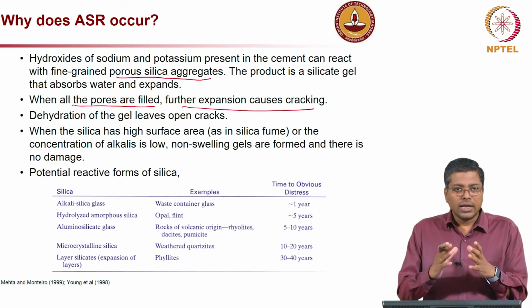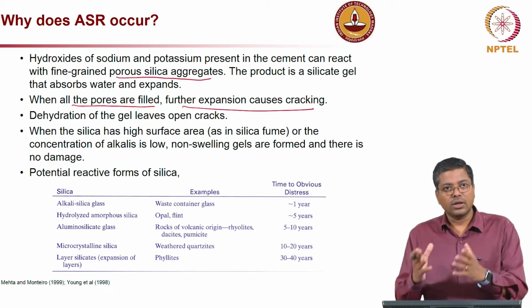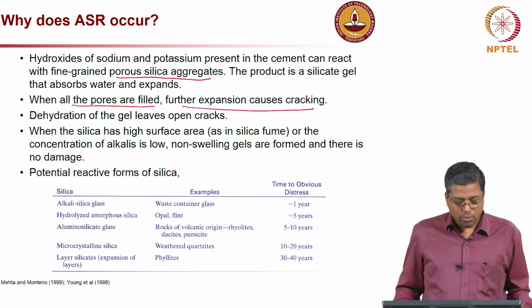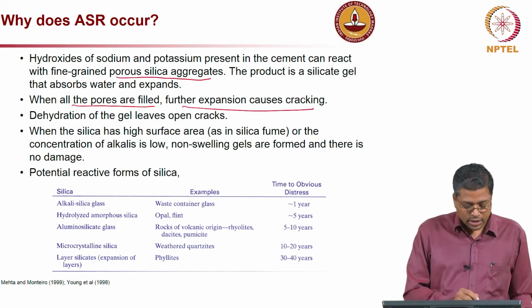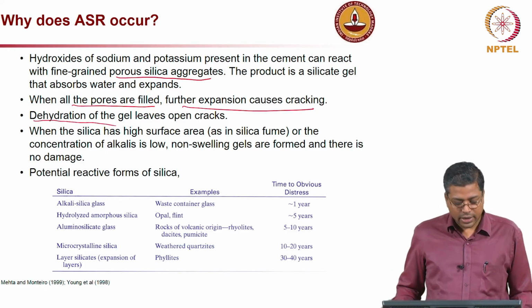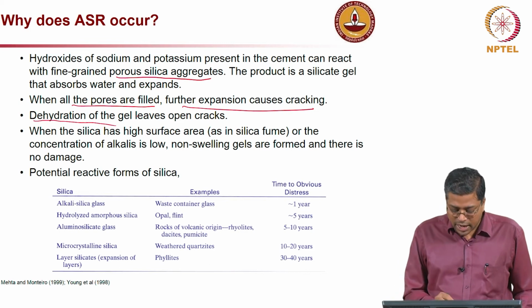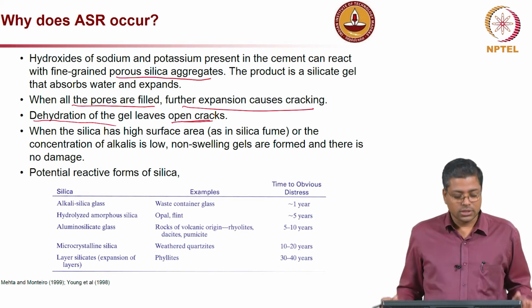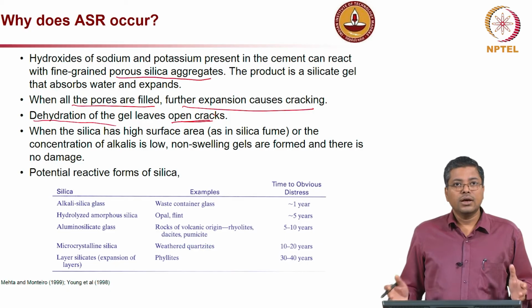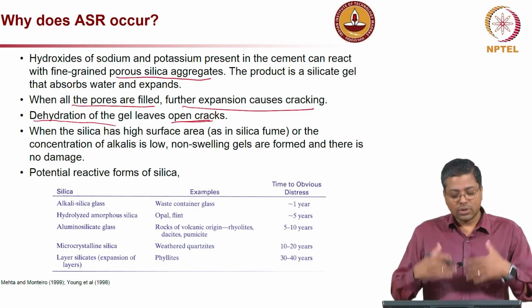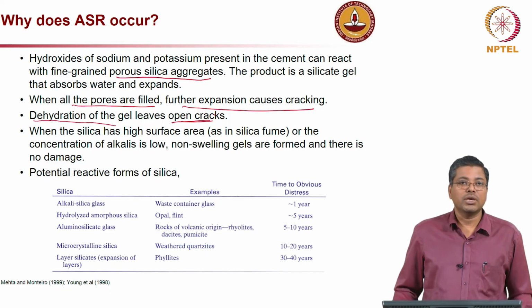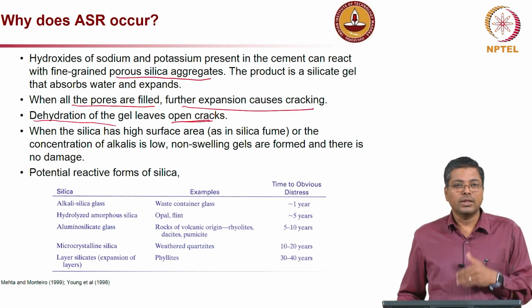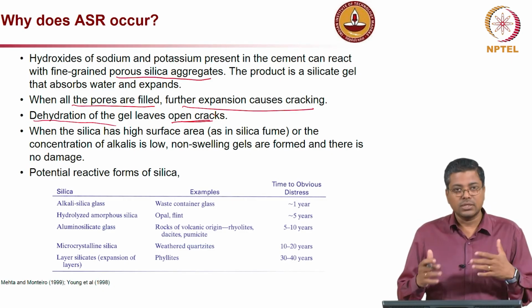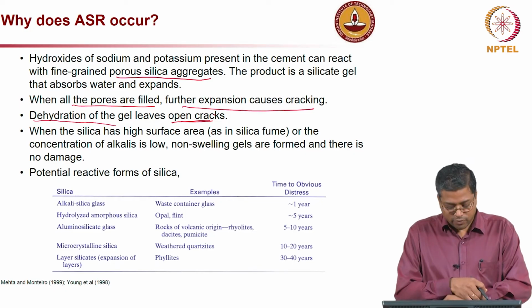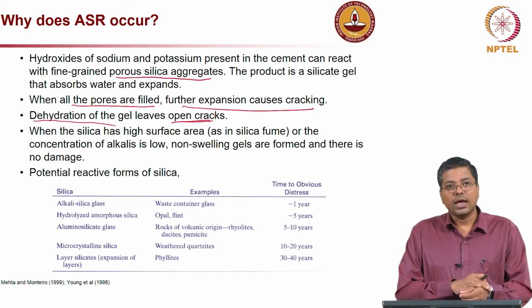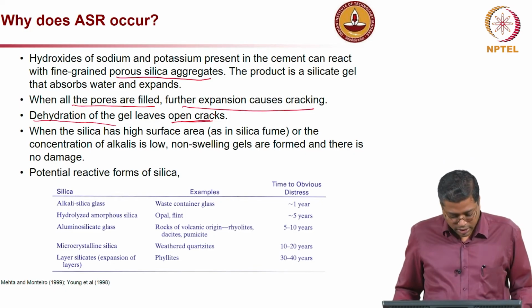Now, let us say there is a dry environment and all this moisture gets evaporated. That leads to dehydration of the gel, which will leave open cracks or voids in the system. Later on, you can again have more moisture coming into the system, and then further reaction can happen, and this can lead to continued formation of more and more gel, leading to significant cracking.